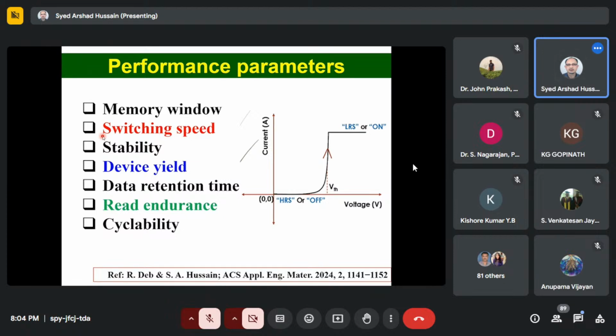For example, you have made, say, a ReRAM device. So you switch your system from high resistance to low resistance state. Now, as per the device configuration, your device will retain the data for a longer time. So you have to study how long it can retain. You write some information, that means you change your resistance state to a desired state, then check how long it can retain the value with an acceptable amount of degradation. Because if degradation or variation crosses certain limits, then it's difficult to use. It will have problems with data reproducibility also.